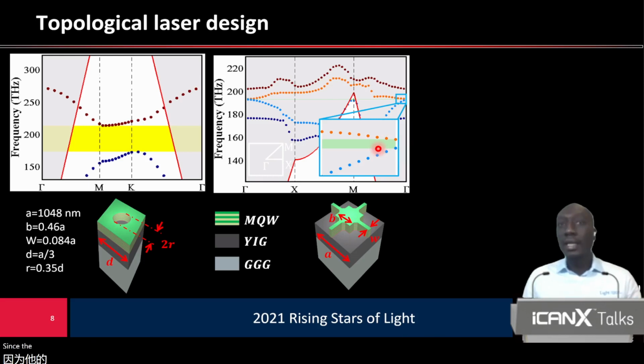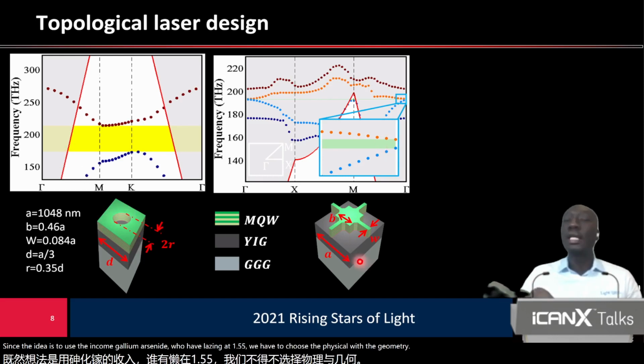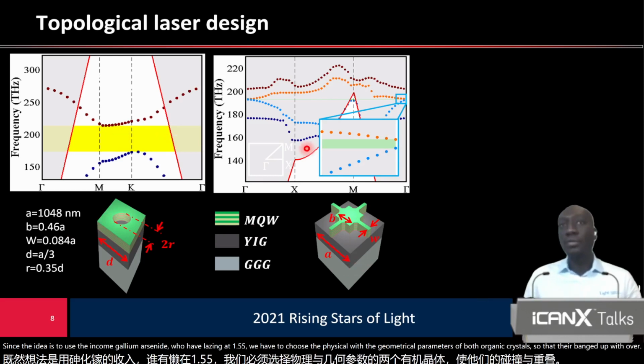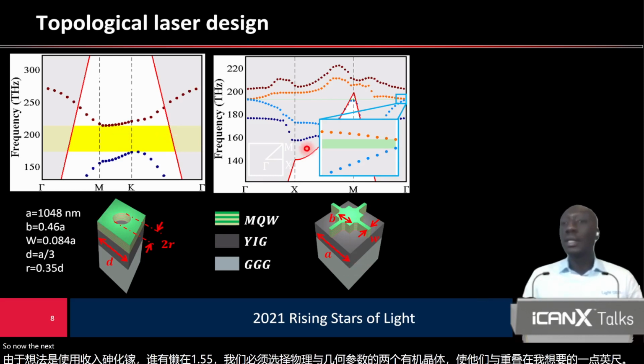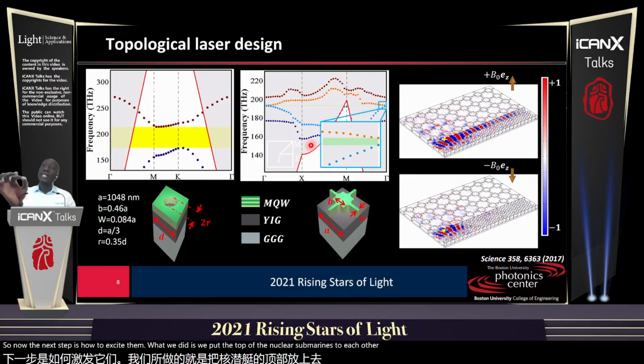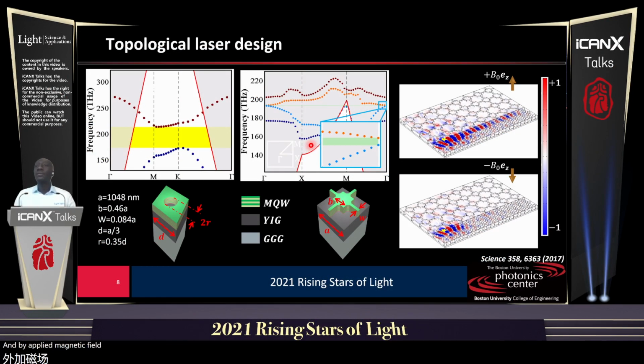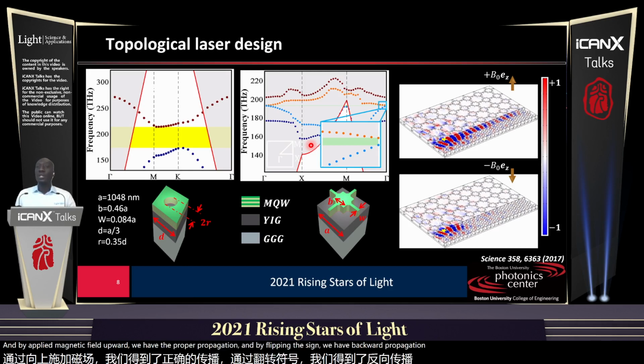Since the idea is to use indium gallium arsenide phosphide to have lasing at 1.55, we have to choose the geometrical parameters of both photonic crystals so that their band gaps will overlap around 1.55. So now the next step is how to excite them. What we did is we put the two photonic crystals next to each other, and right at the boundary we put a point source. And by applying the magnetic field upward, we have forward propagation. And by flipping the sign, we have backward propagation, which shows that we can successfully design a topological laser using a magnetic material to break the time reversal symmetry.